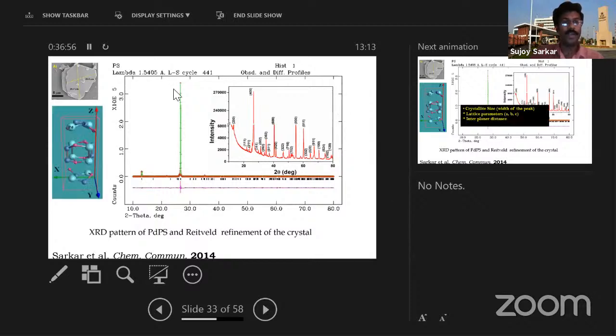We checked that this is the structure of the material, simulated using this XRD software. This is the palladium, phosphorus, and sulfur, and they form a kind of layered material, which we can also see from this microscopy, that it has some layers. So it is a layered material, and the atoms are arranged in this way.